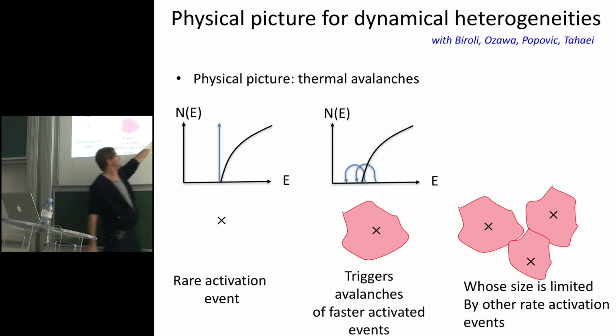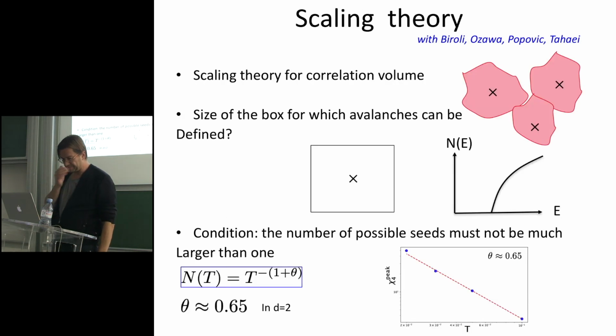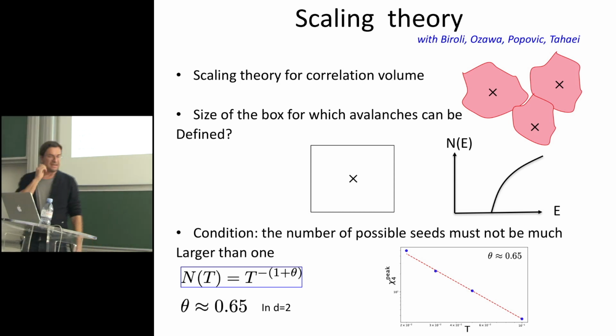And what would limit the size of those avalanches is the fact that elsewhere in the material, you also nucleate other avalanches. Okay? So it's a competition between having one avalanche that grows and others that compete with you, that actually fixes a length scale in those models. So in one slide, I'm telling you the idea of the theory that we have. And it's essentially finite size scaling.